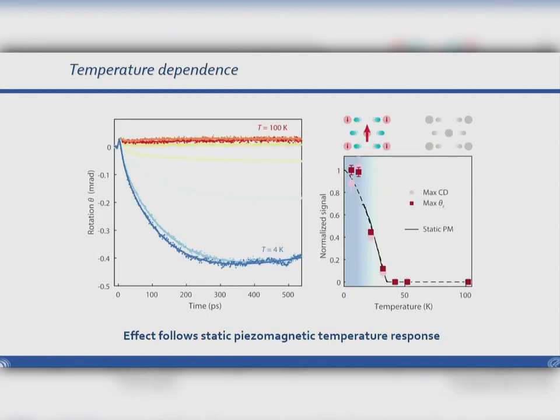And lastly, one check you can do is investigate this effect as a function of temperature. So here are the time domain traces. At very low temperatures, you have a huge effect, but then the closer you go to the Néel temperature, this effect disappears, also shown here. And basically, it exactly follows the magnetic Néel temperature approach once you go down here in higher temperatures.